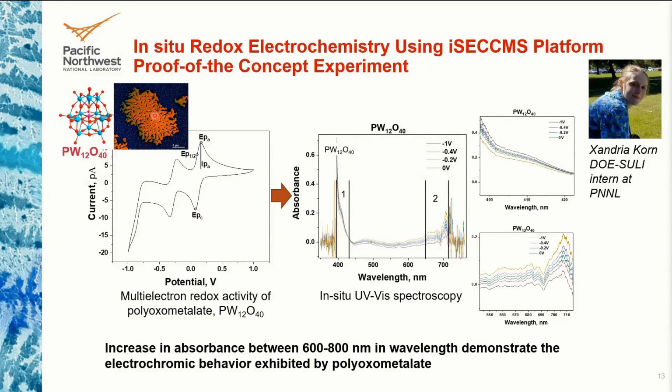when the POM ions are near the surface or on the electrode, as a function of their distribution, is key in many energy applications. For example, if the POM acts as an isolated molecule, we usually observe a high reactivity. But when the POM aggregates near the electrode and forms very nice snowflake-like structures here, the activity tends to reduce because of an impedance in the charge transfer process during the redox